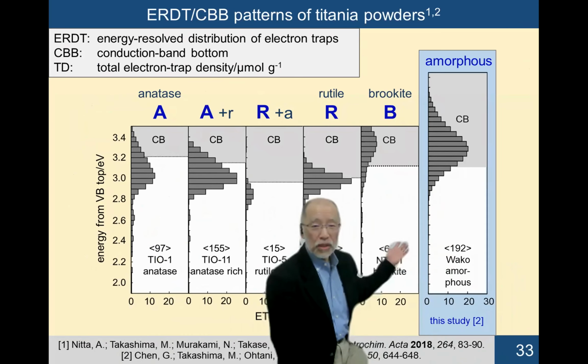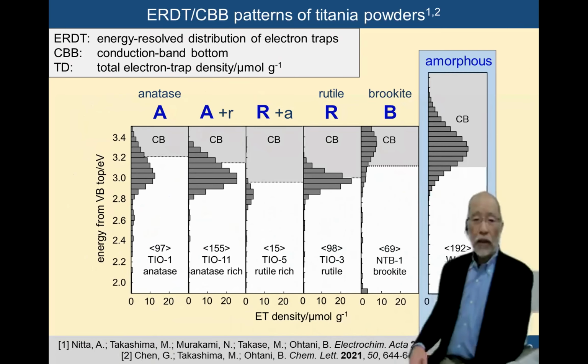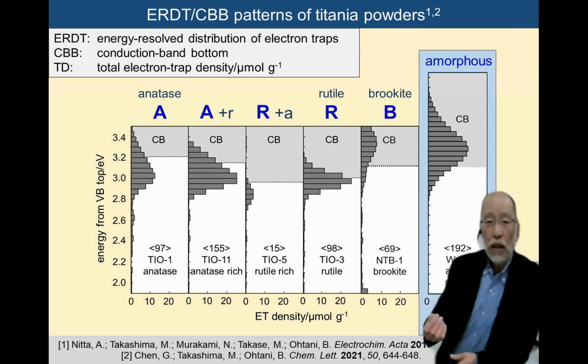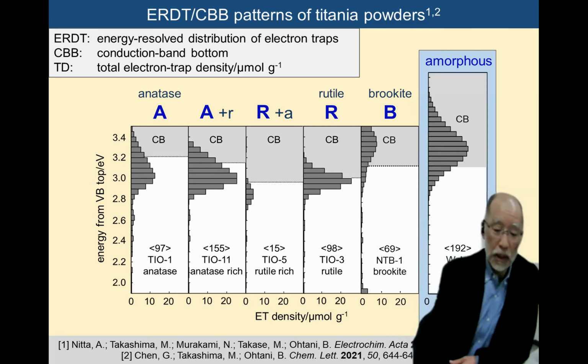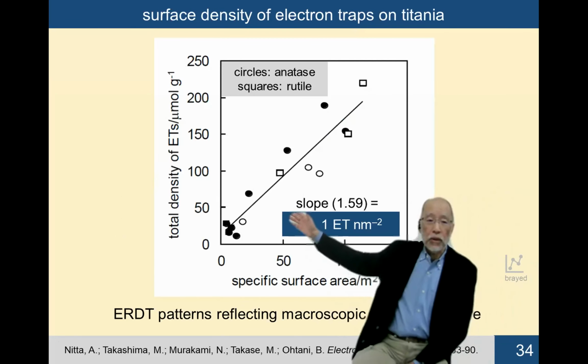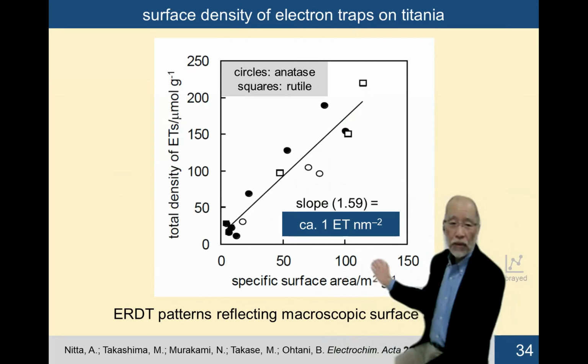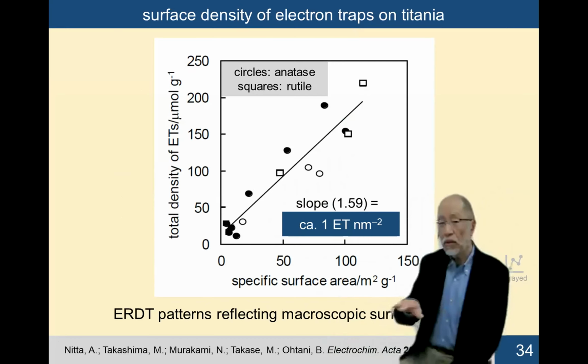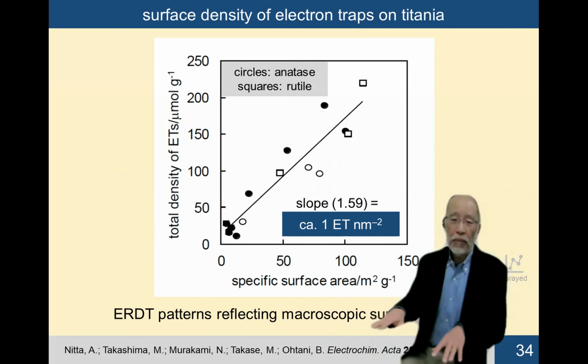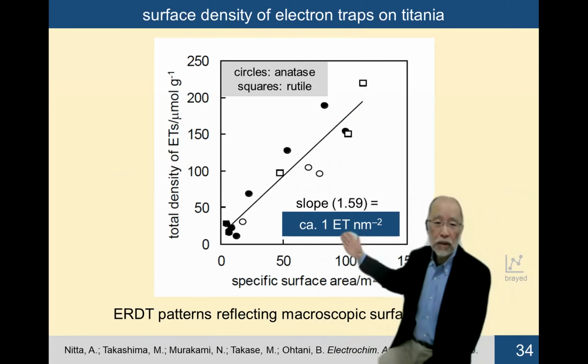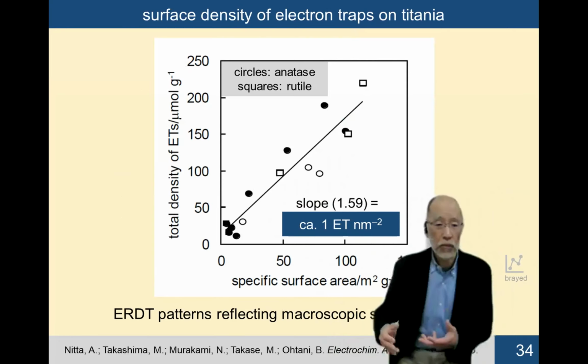But even amorphous titania shows such a pattern, a bit different, at a higher energy position. So even if the bulk structure is completely amorphous, it is possible to obtain such an ERDT pattern. And the important point is that the total density of electron traps increases almost linearly with specific surface area. This tells us that electron traps are located mainly on the surface, and that is not something like a point defect. That might be a surface reconstruction structure. And the estimated density is about 1 electron trap per square nanometer.